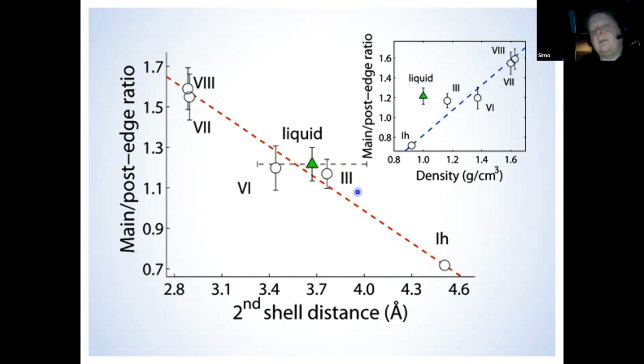Now, why the density increases in these systems is not because the local first hydrogen bonded neighbors would come closer. They actually stay intact in their positions, more or less. The first coordination shell in these phases doesn't change. It's the second shell that comes closer and eventually at highest densities even penetrates inside the first coordination shell. So you have non-hydrogen bonded molecules closer than the hydrogen bonded molecules around the central water molecule.